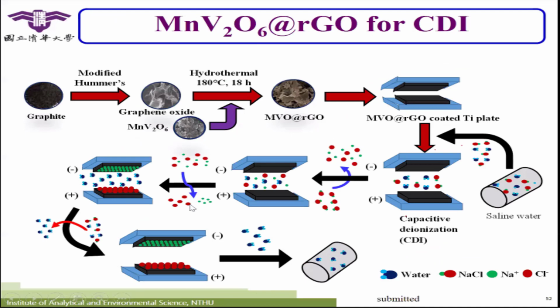You also can try to use some graphene oxide to merge with our MVO here. Then we use the hydrothermal method to coat it on the surface of a titanium plate, and that forms our materials for CDI. In these ways, you always will see that they can remove ions, especially high concentrations of NaCl, and get clean water.